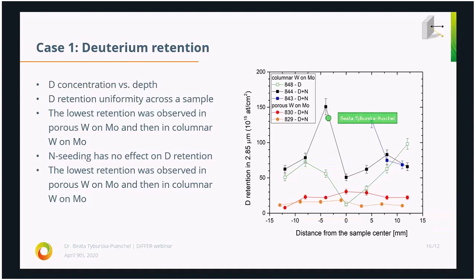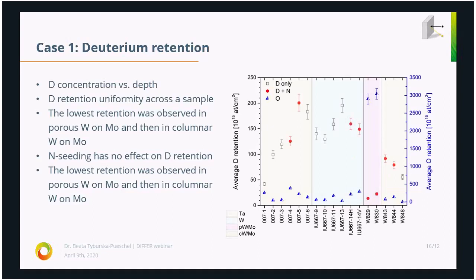But for the columnar tungsten, you can see that usually somewhere in the middle, the deuterium retention is the lowest, and it's somewhat getting higher on the sides. Now it's the question, is this the effect of the temperature, or could that maybe be oxide formation? This still has to be analyzed. And then again, because I collected about 100 data points for all of those samples, I now have more statistics to show, to be able to analyze different effects.